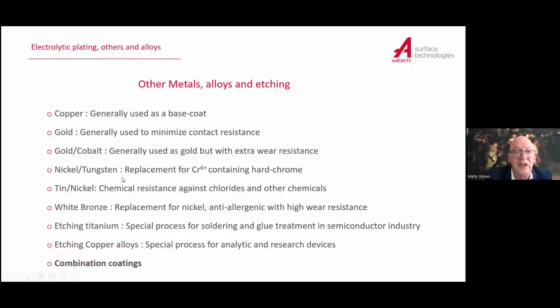You have nickel tungsten. That's a coating which is yet in development, and we use it as a replacement for chrome 6, for hard chrome, and it has good results. It's now running in automotive cars for testing, and we see that it is a very promising coating for replacing the chrome, but still staying on an electrolytic coating system.